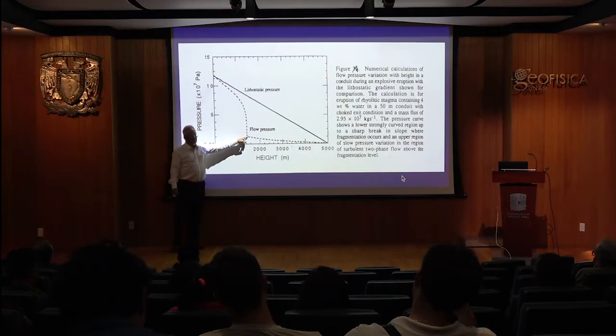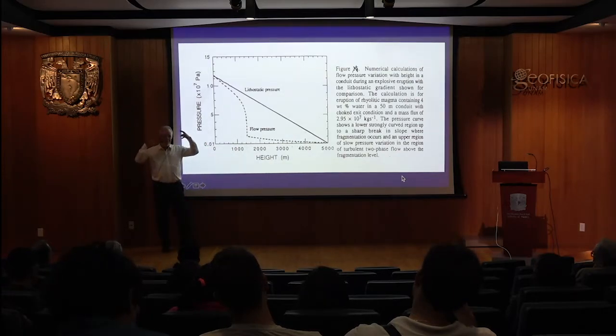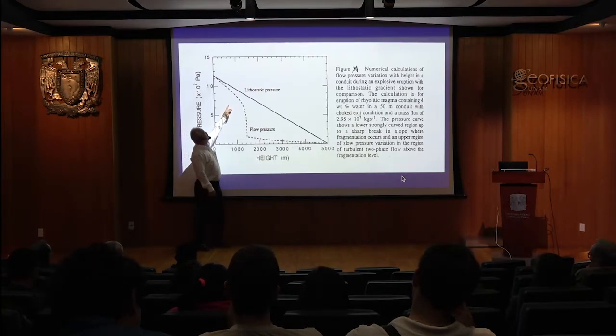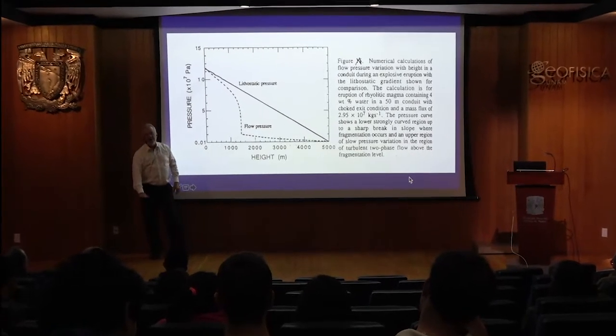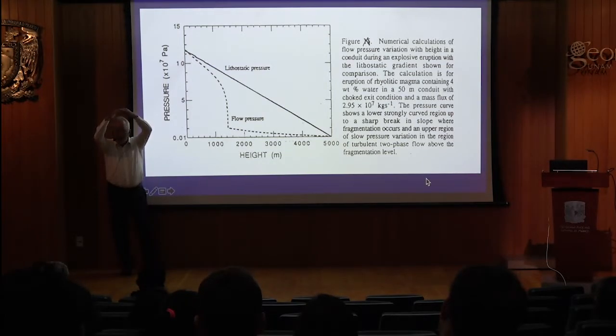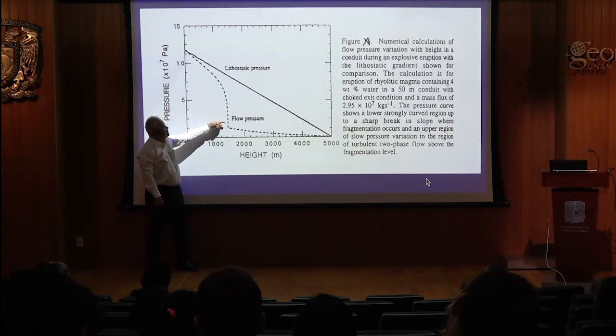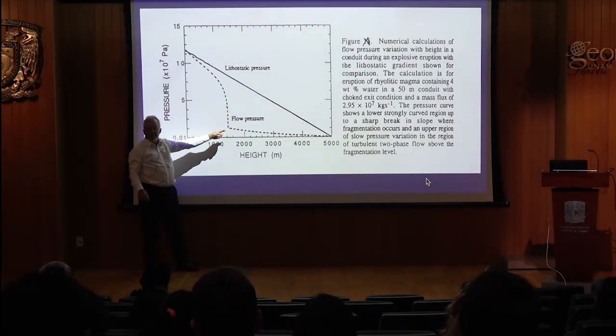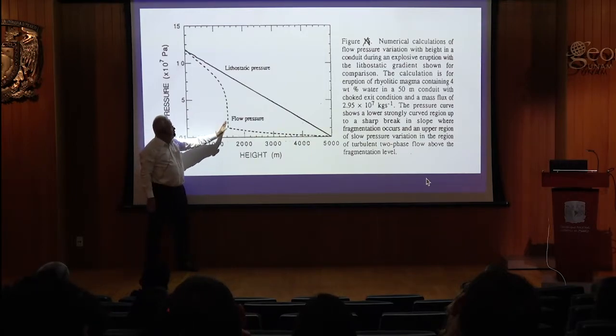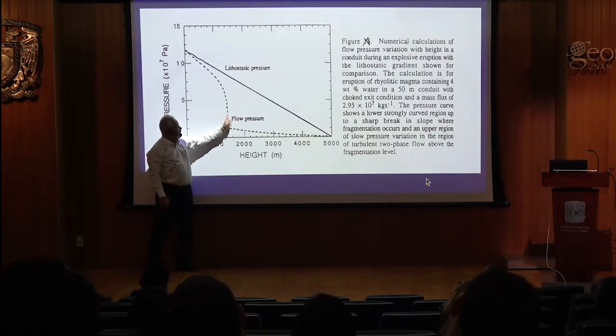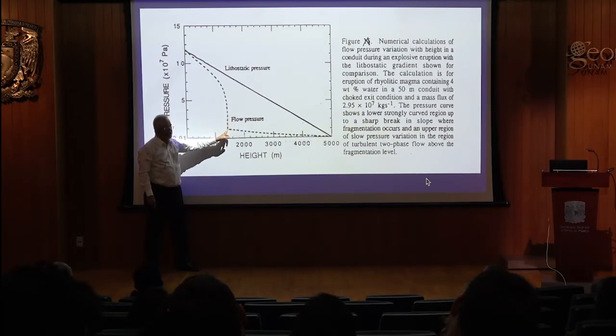But look at the flow pressure. The flow pressure is revolutionary. It's categorically different than the decrease in the weight of the rock. And the curvature of this line depends upon the variation in viscosity of the magma from wet, where it's low, to dry, where it's high. That gradient in viscosity translates into this curvature in flow pressure. And because this is a volumetric stress, when I'm decompressing here, I get a strong decompression rate.